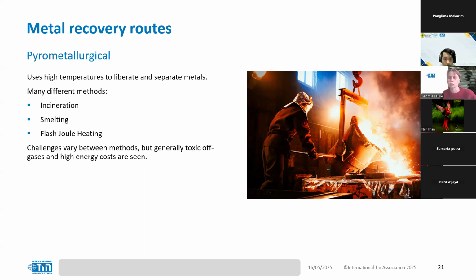Modern incinerators include off-gas filtration systems, so they can capture any metal-bearing dust or vapor for further refinement. Smelting, on the other hand, is another core method for metal recovery, and is already used at industrial scale. During smelting, e-waste is melted inside a furnace at high temperatures with the goal of segregating metals into a molten metallic phase and a molten slag phase.